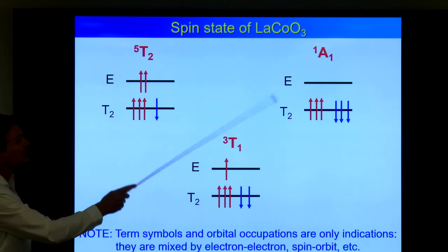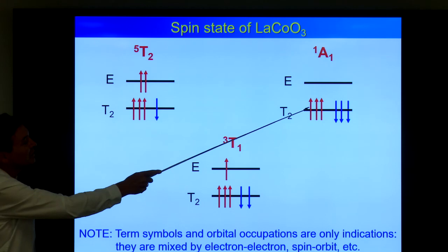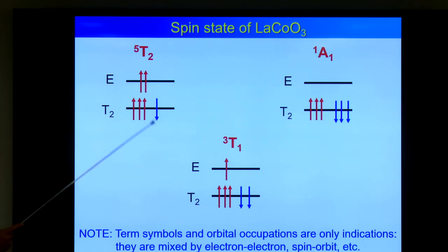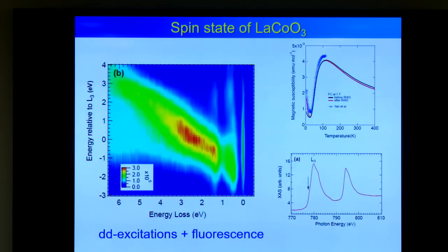At 0 Kelvin, a single crystal of lanthanum cobalt oxide will be low spin. And if you heat up above 300 Celsius, it will be high spin. That's known. So what is the reason that I put the intermediate spin? I quickly go through the experiments.